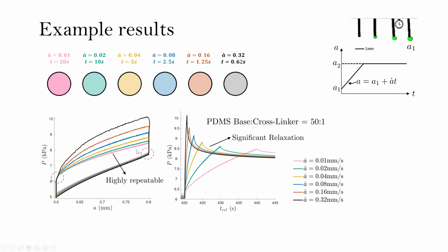This pressure response is the equilibrium elastic response of the material after all the viscoelastic effects have died out, so we use that to extract the purely elastic part of the material response. There is some slight drop in the relaxed pressure as we keep loading the material, which we attribute to probable fatigue, but we do not account for that in our modeling since it's negligible.